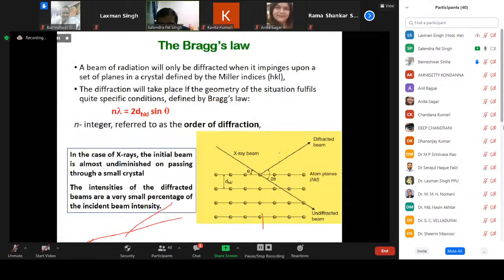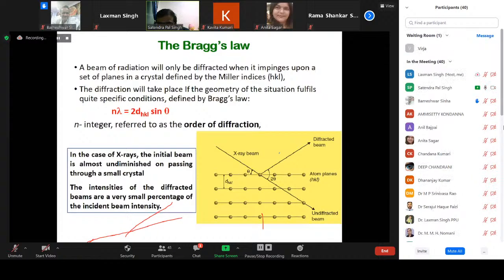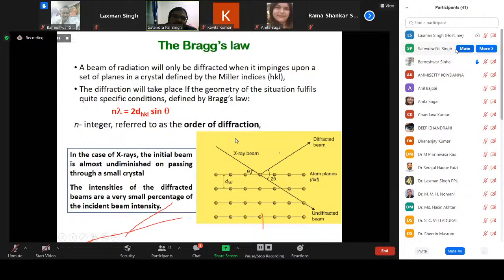Now, why are these X-ray patterns generated, and what is the law behind it? It is Bragg's law. Bragg's law says that only those X-ray beams will be diffracted which satisfy the Bragg condition: 2 d_hkl sin theta is n lambda. n is an integer referred to as the order of the reflection. All the other incident beams falling on the sample, which do not satisfy this condition, will not take part in the diffraction pattern. This is called the Bragg condition: n lambda is 2 d_hkl sin theta.